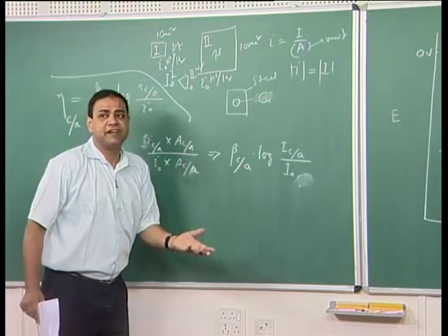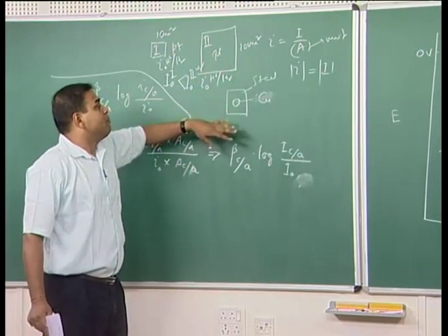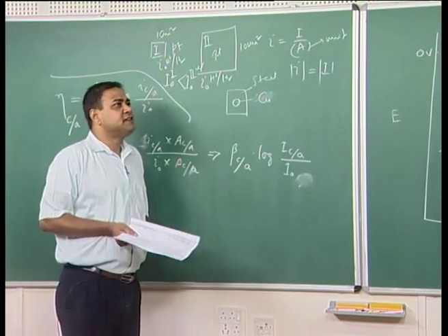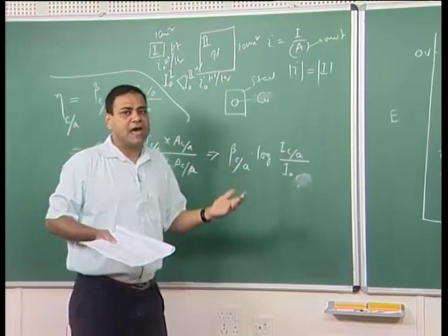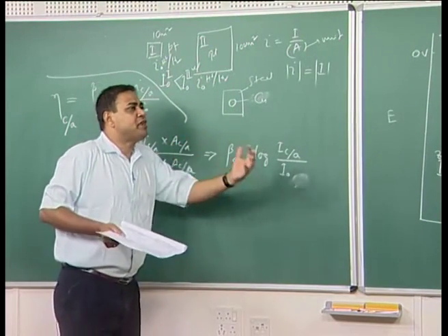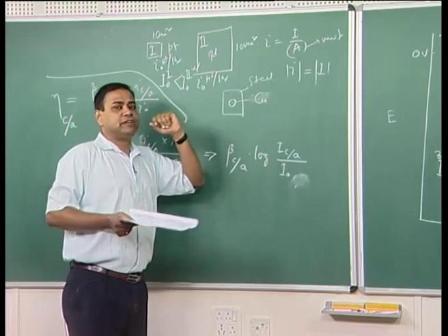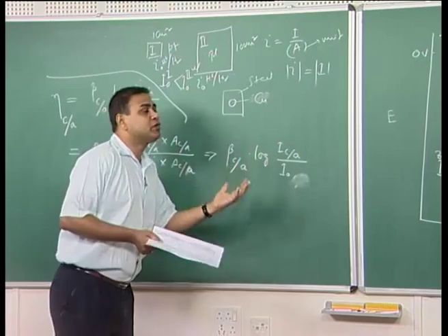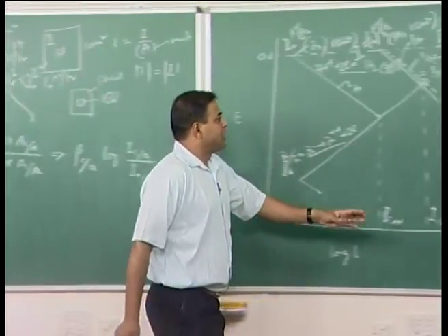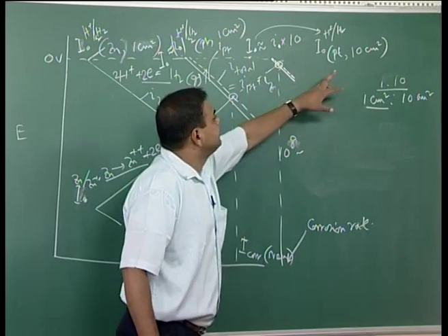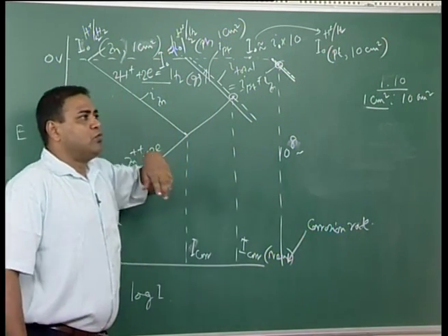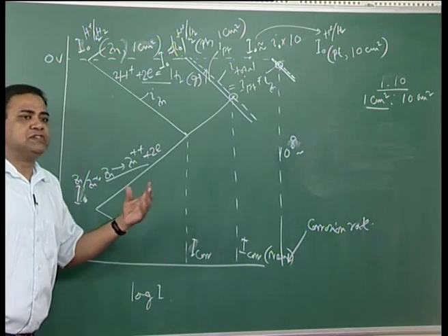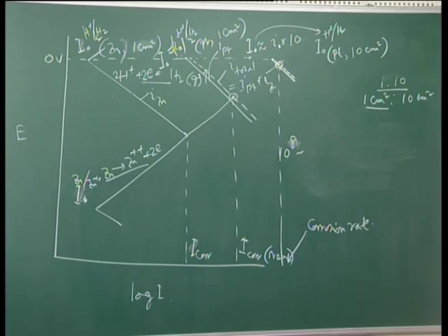Now you see why, when you are using steel as a rivet, the steel is dissolving at a much faster rate, because we are going to have more and more cathodic reactions on the larger cathodic areas. In order to meet that electron balance, I have to supply more and more electrons from the small anodic areas. So, more and more electron supply means more and more dissolution, and that is why we are going to have much higher dissolution if you combine it with a platinum which has 10 times more area than the active metal, which is zinc. So, this is one more example.